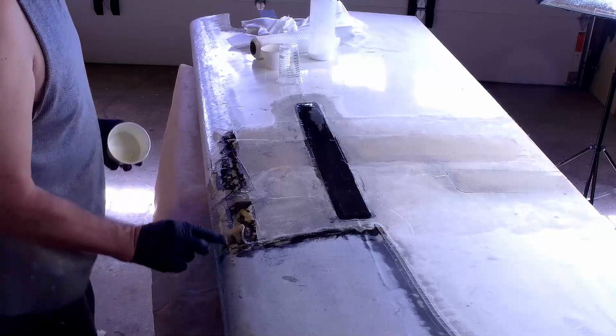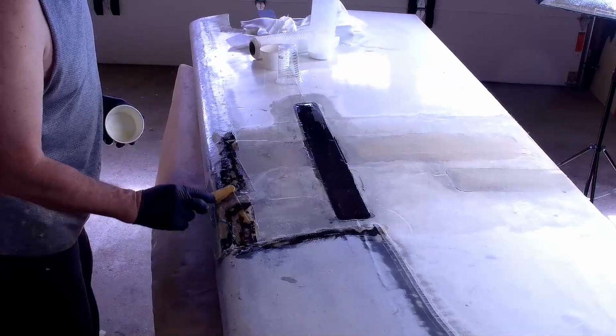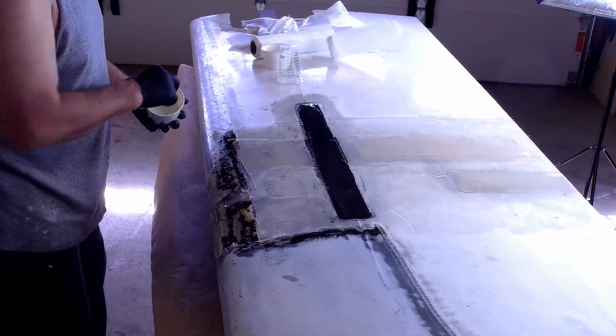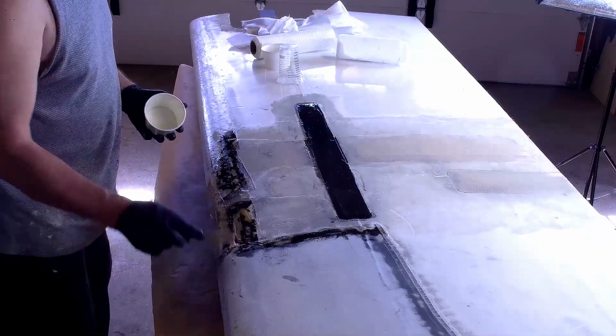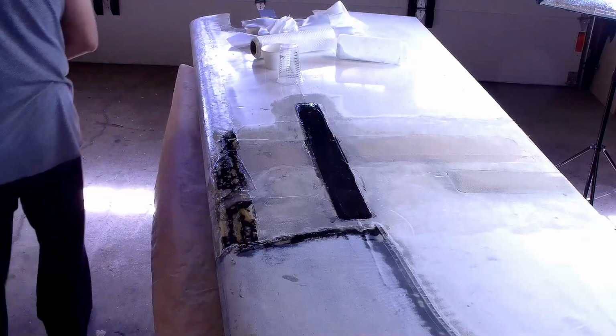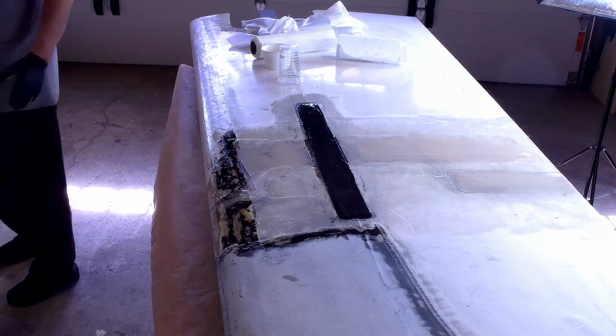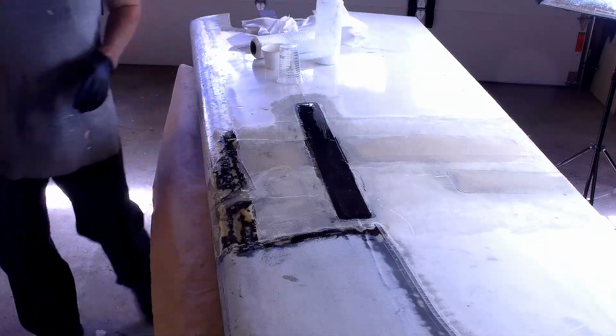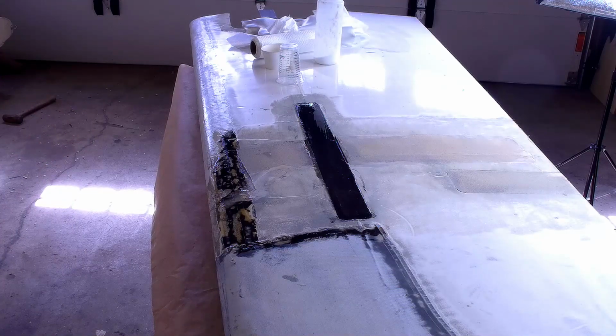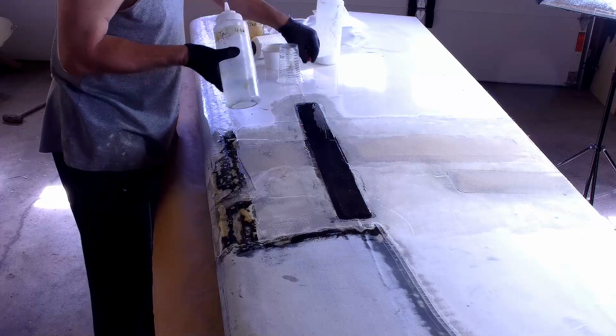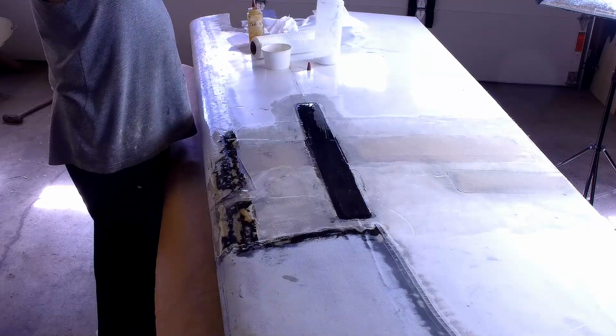You're also watching me apply structural adhesive to some carbon fiber at the leading edge where there were repairs done due to previous testing and other changes. I want to make sure that the new skin is firmly bonded to that leading edge area. And the area where the main wing skin is, it's Kevlar, 120 Kevlar, and I've roughed it up with sandpaper, and if you know Kevlar, you know it's got a lot of fuzzies on it, and those fuzzies provide a tremendous bonding surface, so it really doesn't need additional structural adhesive on it. The bond of just standard laminating resin over that roughed up Kevlar will be just fine.